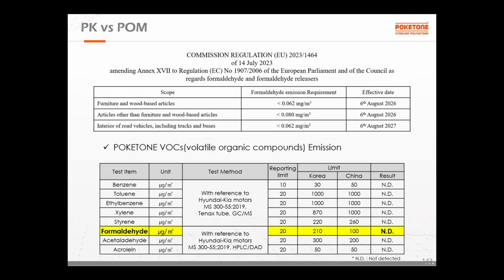POM is a good material and good enough, but especially in Europe and globally, toxicity and emission regulation has been enhanced. And this one is for the European regulation. The emission requirement for formaldehyde is this minimum number at least. And polyketone shows no detection, not only for formaldehyde but also for benzene, toluene, xylene, styrene, and acrolein. In every area, no detection. So for VOCs, we can consider entering the market. Actually, in Europe, automotive interior parts regulation for toxicity has already been enhanced. Then polyketone can be a great substitute material.